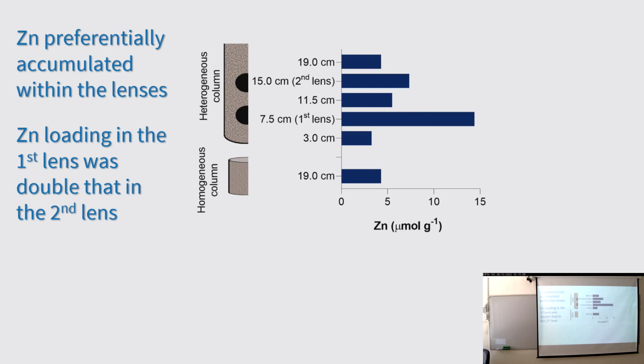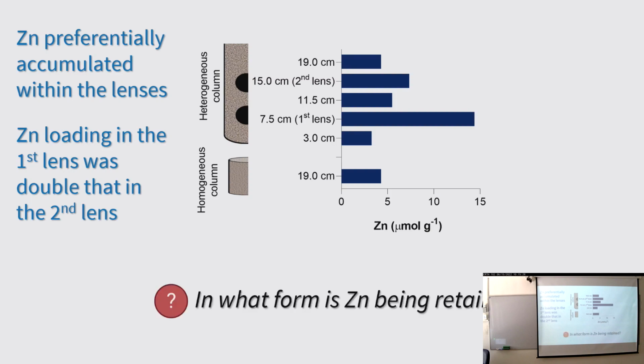We see that for the sand, the levels are more or less similar. However, for the lenses, we see that the first lens has accumulated nearly double the loading of the second lens. So this figure shows us that zinc is indeed being retained, and to what extent, but we don't know the form in which it's being retained.